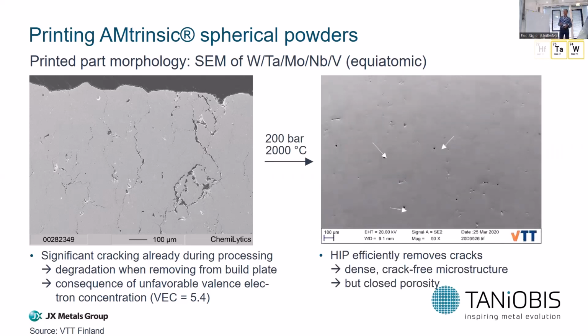This was done here, for example, for this sample at 200 bars and 2000 degrees C. And what you see is that you more or less completely removed the cracks. This is quite surprising, because these are open structures. Nevertheless, we could remove them, but what you see is residual porosity. The arrows are not on the slide, but they should be. But the point is, you can effectively remove the cracks and end up with dense and crack-free microstructures, but closed porosity.